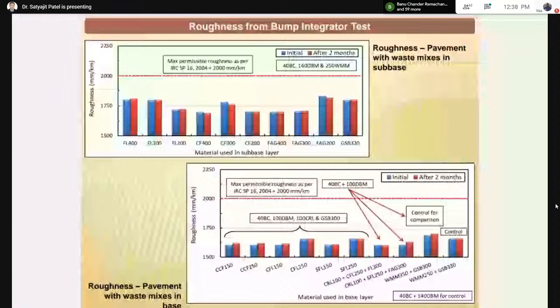This figure indicates the roughness index IRI value, which has been obtained in the range of around 1600 to 1800 mm per kilometer, and the limit is 2000 mm per kilometer for the airport runway or for the super highway. So even after 2 months of construction, that value is quite low, around 1600 to 1800 mm per kilometer for all the waste materials.